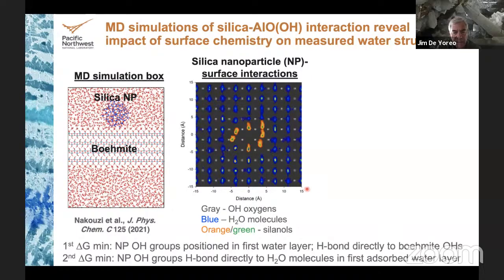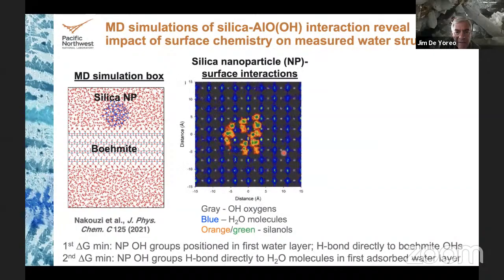Let's see, have I said that right? The OH groups position the first water layer, which are hydrogen bonding directly to the OHs of the boehmite, just like in our experiments. But when you go to the second hydration layer, what you now find is that what we're measuring is the hydroxyl groups interacting with the water molecules in the first layer. So it's a complicated story.